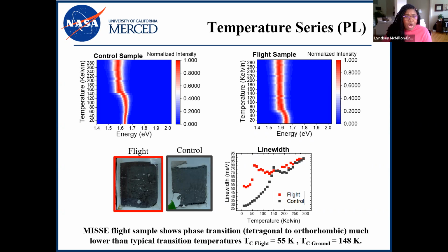So our takeaway here is that the MISSE flight sample shows a much lower phase transition than typical. And we're starting to really feel that the presence of all those small defects on the surface of the MISSE flight sample might be helping to stabilize the material. And the material itself actually seems to be better for having gone to space, which was not what we expected, but it's wonderful.